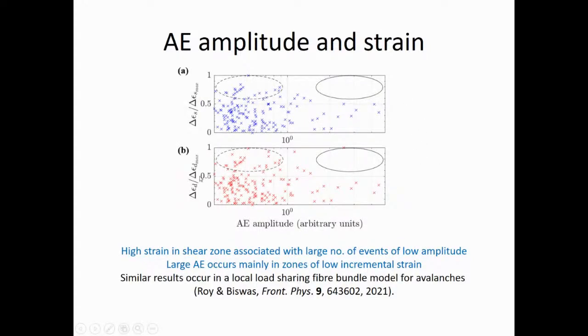And this was a surprising result. We find that the acoustic emission amplitude is highest in areas of low strain. Okay, so there's a sort of negative correlation between the strain and the acoustic emission amplitude. This is a surprise, but it's maybe not surprising given that we see so much evidence of aseismic deformation on the shear band. It's also a result which is expected from a fiber bundle model for avalanches in a more generic sense, which was published recently. But this does have implications for our inferring properties of the deformation from just looking at the seismicity alone.